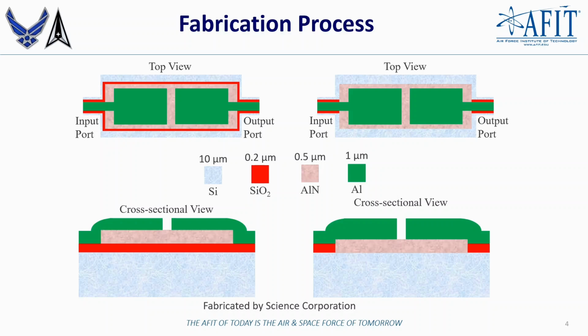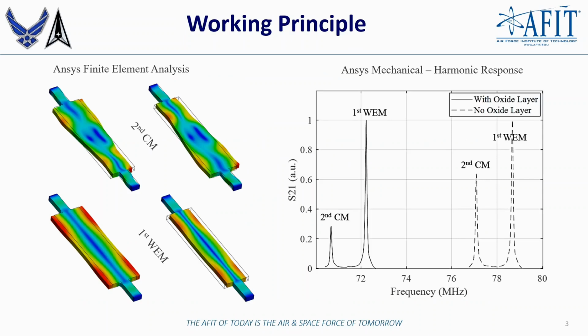The dimensions were carefully designed so that the two adjacent modes are close in frequency to simplify the calibration and characterization. On the right here, we can see the harmonic response. The solid lines represent the resonators with the oxide layer, while the dashed lines show the resonator response without it. The oxide film improves the quality factors by acting as a buffer layer, smoothing surface defects, and enhancing bonding between silicon and aluminum nitride.